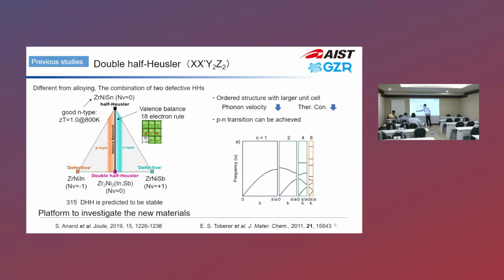Both end members are not stable as a single phase, so you have to mix them to get a single phase. That's the interesting idea, because it's not just alloying. More than hundreds of double Half-Heuslers are predicted to be stable from DFT, and this can be a new platform to investigate new compositions.